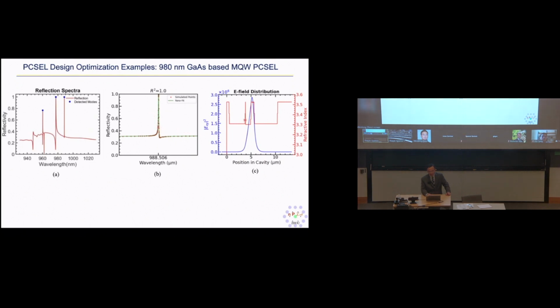And then this one shows the index contrast of the heterostructure, as well as the mode overlap, basically the field overlap I showed earlier. So make sure the overlap of the E field with your PC lattice as well as the quantum well regime gives a so-called confinement factor and a coupling coefficient, etc., for low threshold lasing. So those are a few outcomes based on the design.